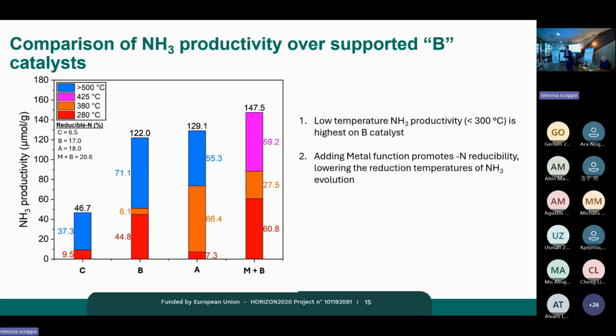So as you can see, during this first year of the project, we have been very busy trying to create materials that can do this job, and we have some very good leads at the moment. Now the next period is going to be about doing the full kinetics, because this is just a temperature programmed reduction experiment. So we have to now test this under reaction conditions and see what is then the turnover frequency of these materials and benchmark them against conventional ruthenium-based catalysts and also iron-based catalysts.